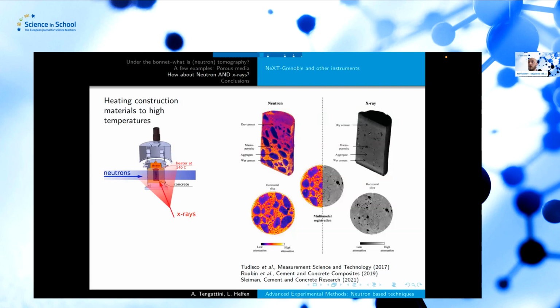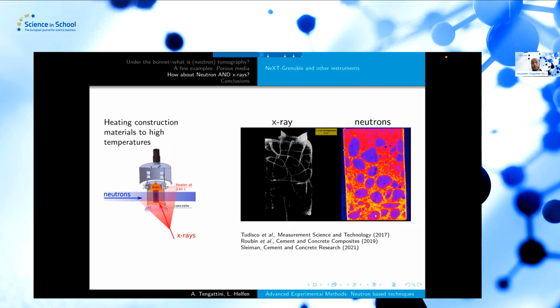But it's very hard to distinguish the other two components, which are the cement paste and the aggregates, so the large chunks of rock that are inside the concrete. Conversely, in neutrons, you can see very well this cement paste because it's full of hydrogen, but both the pores and the aggregates are somewhat transparent. So it's only when we combine together these two information that we can do what we call a segmentation, which is being able to accurately say, well, this bit of my concrete is an aggregate, this bit is a cement paste.